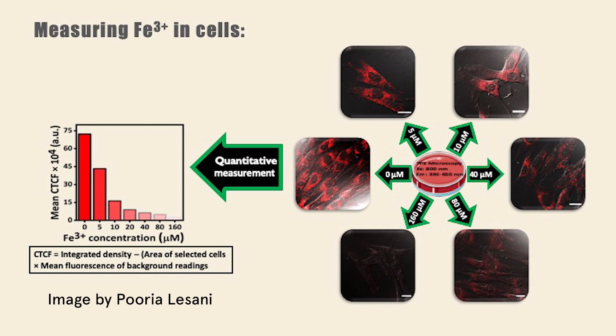I measured the average fluorescence of the cells to see how the ferric ions are affecting the fluorescence emission of the carbon quantum dots in the cells, compared with the sample which only has carbon quantum dots. The results clearly show that by increasing the ferric ion concentration, the fluorescence intensity of the carbon quantum dots is decreased. These results provide reliable quantitative measurements of average intracellular exogenous ferric ion using two-photon fluorescence imaging. I hope you enjoyed this demonstration.